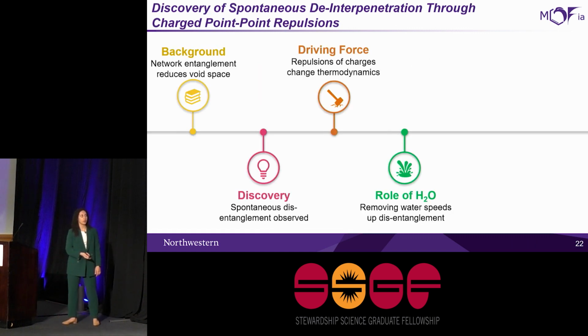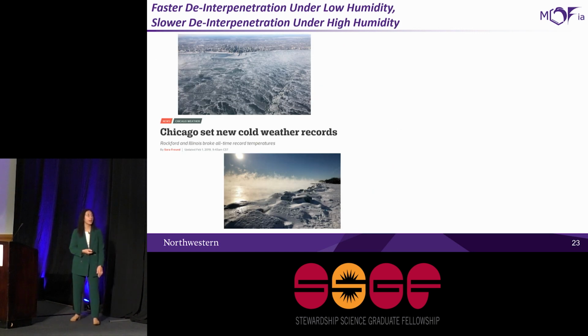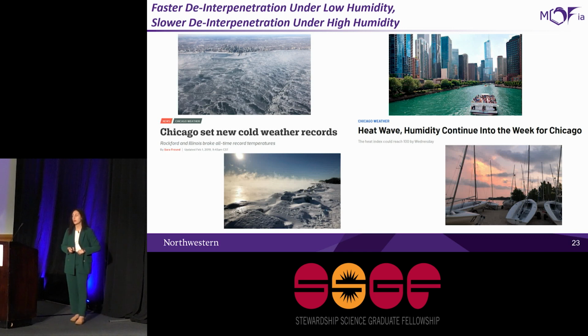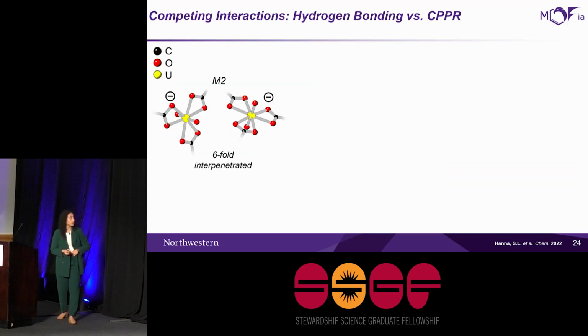So then I actually noticed something really interesting in this process as I was monitoring it. I noticed that during the cold weather in Chicago, de-interpenetration happened really quickly, whereas when it was super hot and we had humidity, it happened a lot slower. So this showed me that water must have been playing some sort of role in this transformation. So I looked a little more deeply at the structure, and what I saw from the single crystal structure actually was that there was a water molecule hydrogen bonded between these two nodes in the interpenetrated structure.